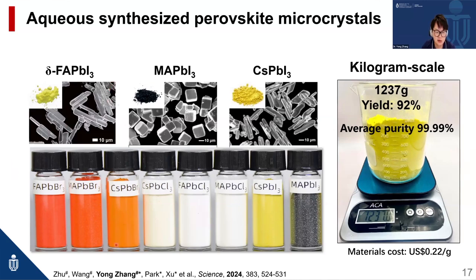This method can also be extended to other kinds of 3D perovskites, and can scale up to the kilogram scale with a high yield of 92% and average purity over 99.99% by removing impurities inside the raw materials.